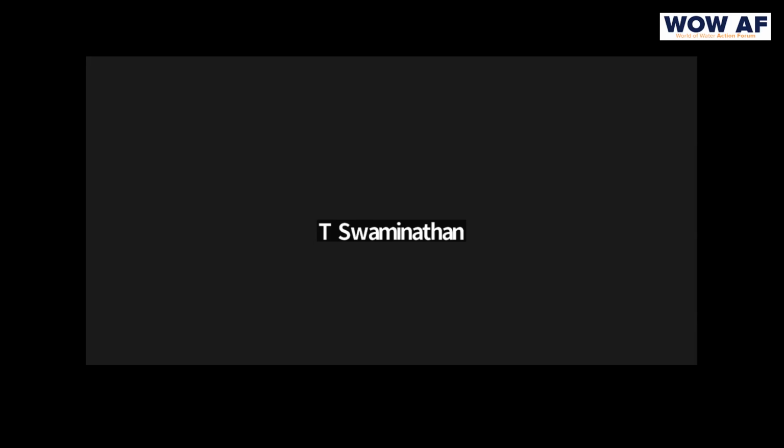Yeah. So the earliest development of the membrane technology, RO technology itself, with cellulose acetate membrane, was pioneered by an Indian. Then followed the later development of polymeric membranes. Most of this was focusing on seawater desalination, where sodium chloride was to be removed. All these membranes necessarily had to have almost 99% removal of the salt, and with that kind of osmotic pressures, the recoveries were less than 40%. So that is where the question of large-scale wastage came.